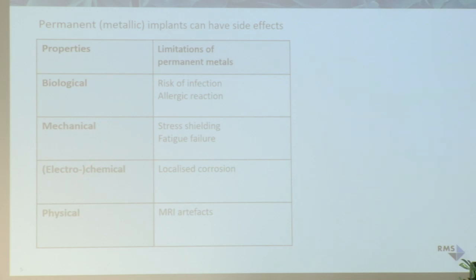Electrochemical-wise, you may have localized corrosion on steels, for example on sites where you have laser markings. And finally, on the physical side, if you look at imaging, titanium and steel cause artifacts in MRI, so you have a shade around the implants where you can't see what happened with the tissue.